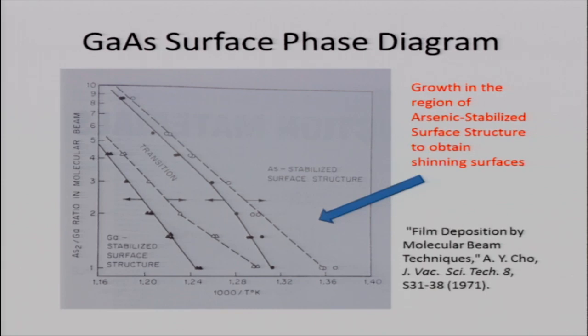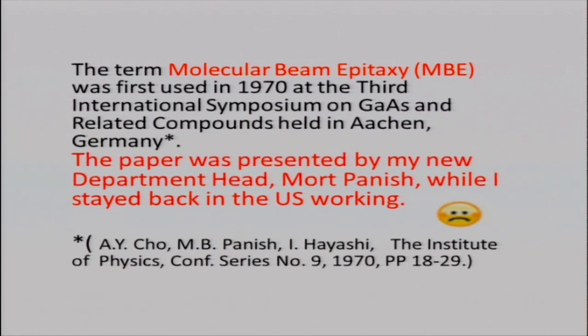But too much gallium on the surface, what happens? You get gallium beads on the surface. You get a hazy surface, finished. Okay. So therefore, we always grow on the arsenic stabilized surface structure.